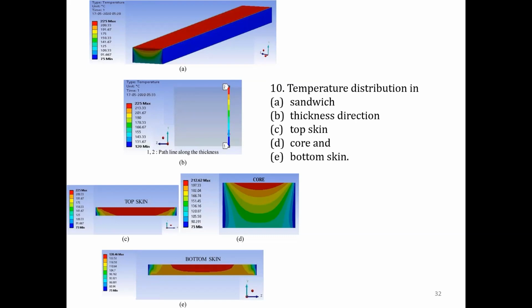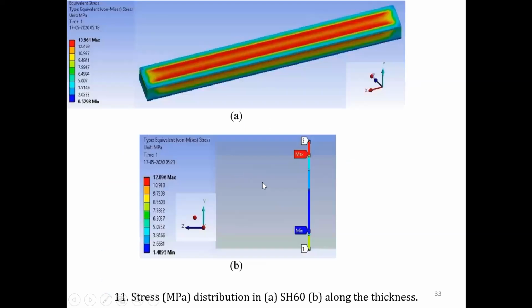So the thermal analysis results of these sandwiches are imported as load data for analyzing the thermal stress distribution. And we applied similar boundary conditions, and they are imported for the structural analysis, in addition to a frictionless support for the bottom surface. Now, what did we observe? Stresses are found to be maximum in the top skin near the lateral surfaces and minimum at the core, which you can see here in figure 11A.